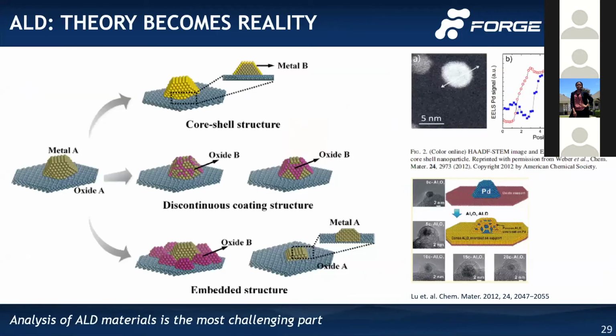Some areas where theory can become reality and may actually be beneficial are these core shell structures. Here's an example: with palladium and platinum core shell materials, the deposition of metal will preferentially go to the metal surface due to energy differences. Materials will always go to the lowest energy state, so sometimes you can selectively deposit material where you might want it to form these core shell structures.